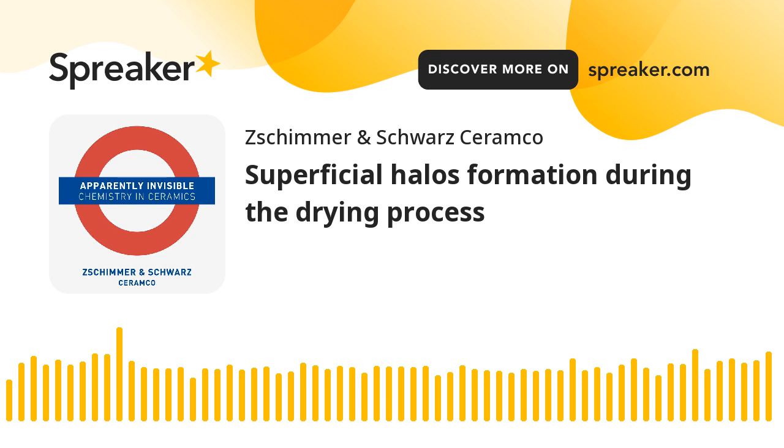In general, all anions and cations that do not form insoluble salts within the system, or that are marked by a low mobility due to their conformation, do not chemically bind to the mixture and tend to be carried by the water to the surface.